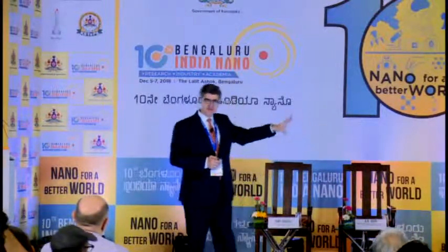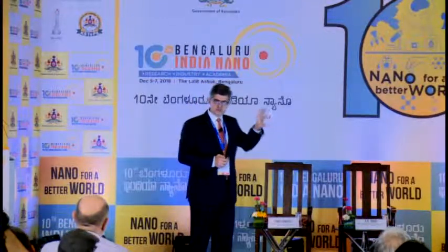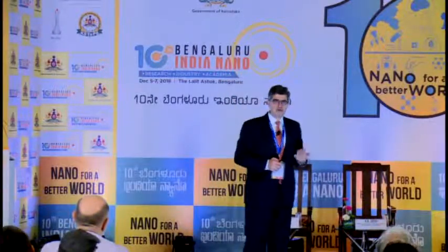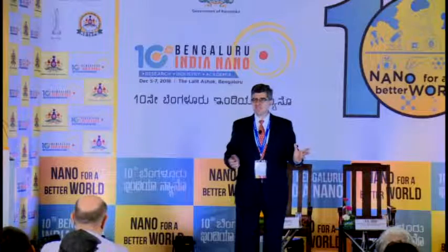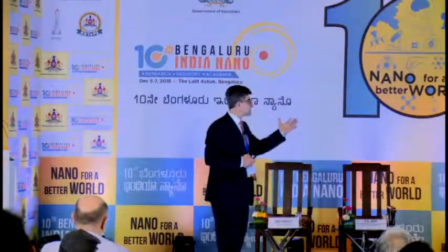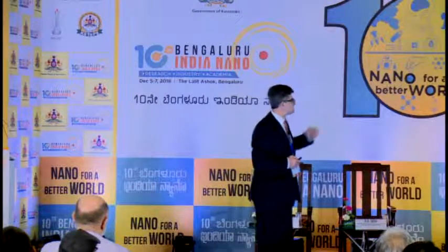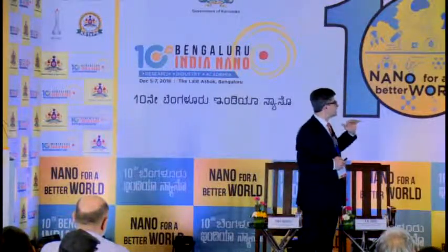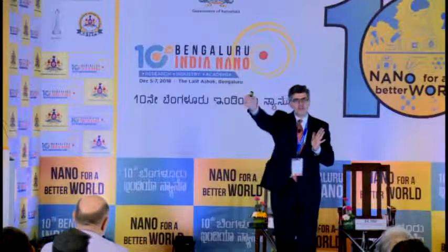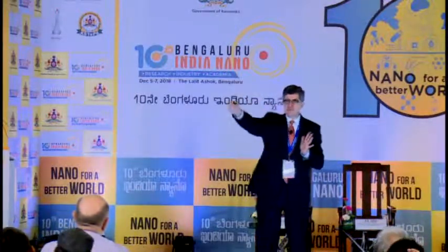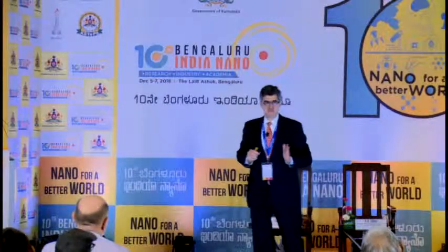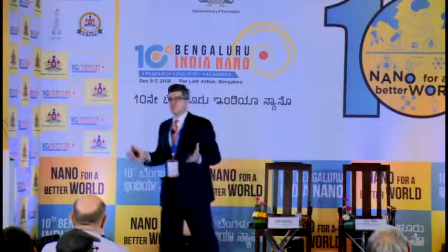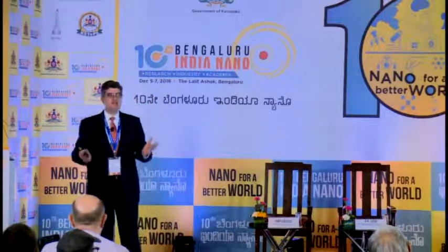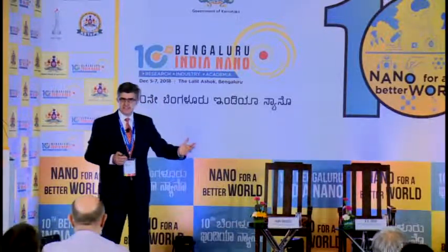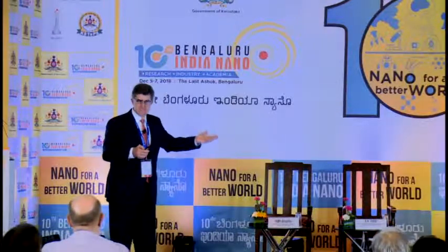It's actually thermodynamically driven, so those are metastable structures, and it's really thermodynamics that tells whether a random solid solution will be formed or a layered structure like that. But what is important, we access a variety of properties. As I mentioned, more than 30 have been produced. And a group in Sweden 2 years ago produced ordered divacancy MXene, considered to be like a monatomic string of atoms. Every third one is missing on the surface. So basically, we can truly push design at the nanoscale to an unbelievable level. We can manipulate atoms and we can create building blocks that can be used here.